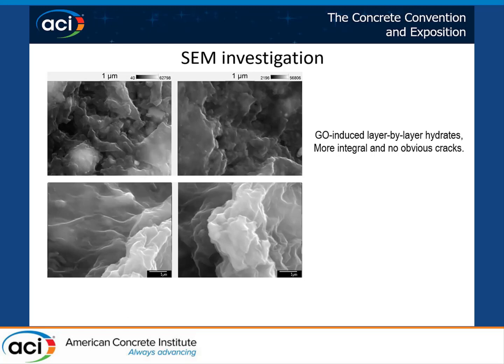And so I think the main reason for this result might be the template growth role played by the graphene oxide, also known as the seed effect, that provides a growth point. The hydrates will grow on this point and then generate a layer-by-layer structure.